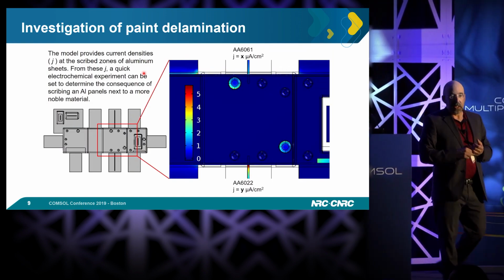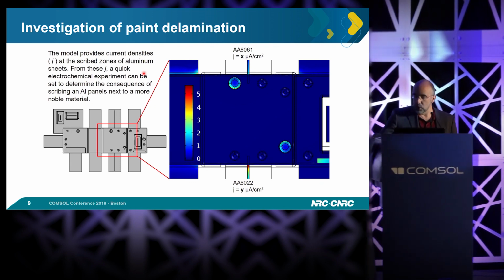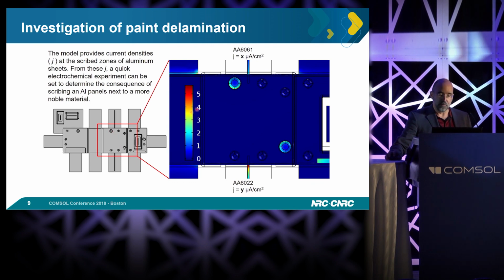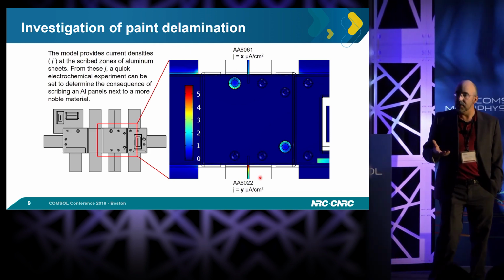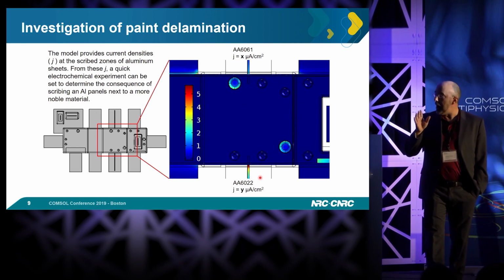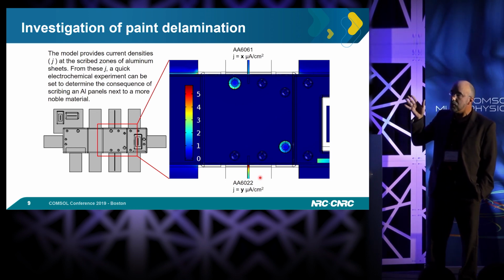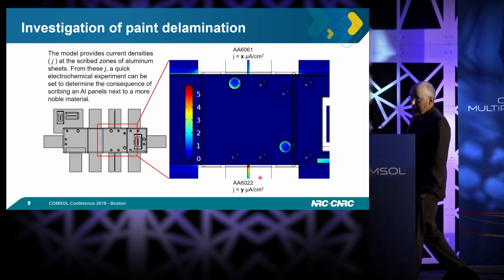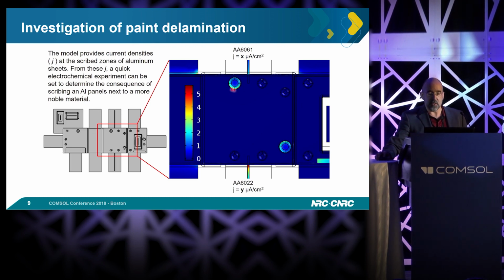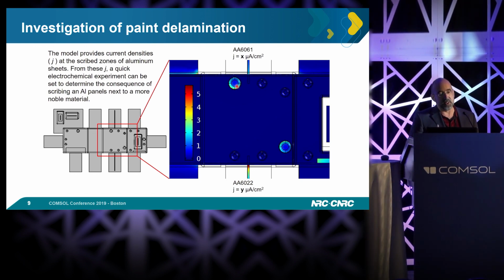Another thing we can do, let's say you have this material here. So in the center, this is a CFRP. You have three stainless steel rivets, an aluminum rivet, and two aluminum components, 6022 at the bottom, 6061 on the top. And those samples are painted. The aluminum is painted, except for a teeny area in the center. We have scribed the surface. So what you see here, this rivet, we see an anodic current on this one. So this one is going to be dissolved. And it's never a good idea to use a rivet as a sacrificial component, from what I've learned, at least.